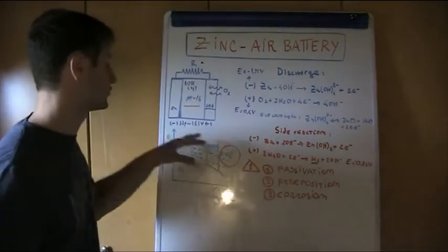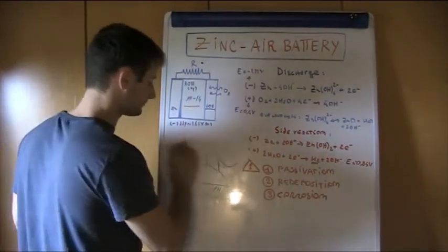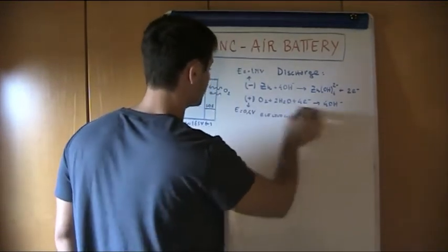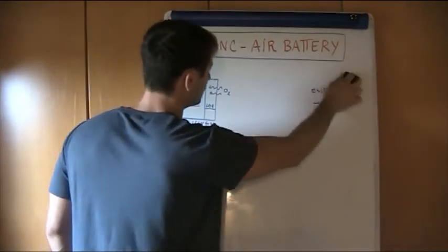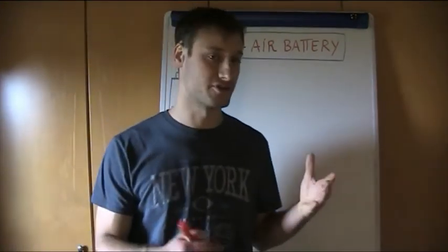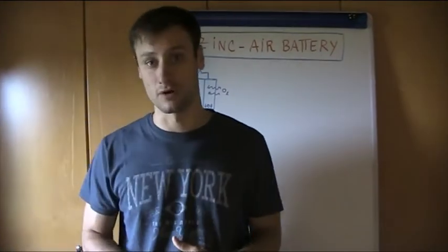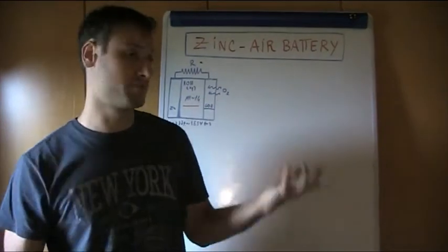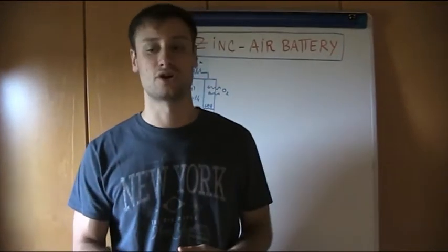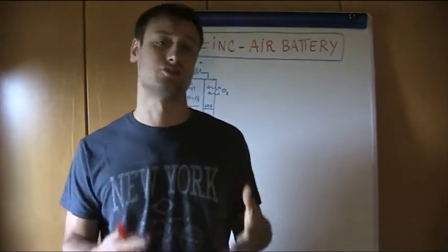And so these problems concern the anode, but for what concerns the cathode, we have, for instance, the fact that, as we described in the first video, speaking in general about metal-air batteries, since we are taking oxygen from outside, even if we are saving weight, in certain situations we have difficulty achieving our function, and the battery can't work. And also another aspect is that when we are exploiting high current, since oxygen is taken from outside, we have problems in the diffusion and we have huge overpotentials involving mass transport.